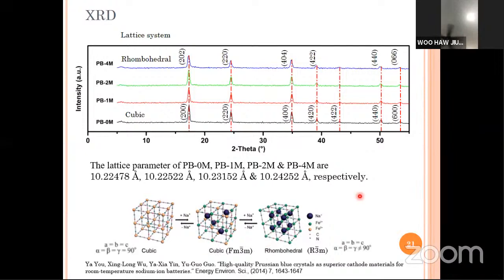So in our case, we are not running charge and discharge here. We are preparing a sodium-rich Prussian blue, and yet we obtain a similar result in terms of XRD. So we concluded that it is very possible that in the sodium-rich Prussian blue, the additional sodium is actually embedded inside the crystal unit cell, and that may cause a little distortion to the cubic lattice system.